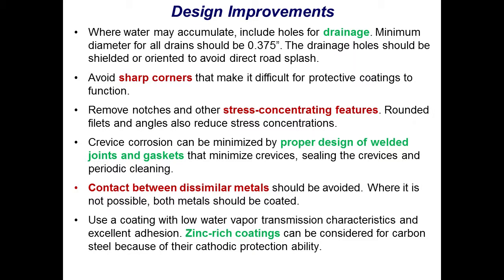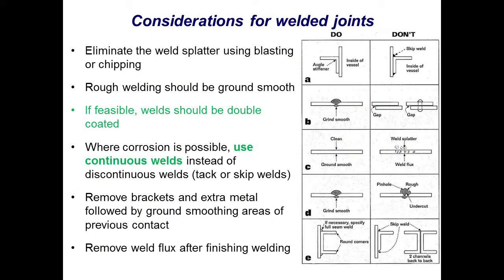Now, in the industry, it's very common practice to use zinc-rich coating. The reason is we have no confidence that without the zinc, the coating will do a good job. For instance, if that coating is dented, that area becomes a weak spot, and that case is probably not much better than without the coating. You have localized corrosion going on. It's a self-accelerating process. With the zinc, the zinc will sacrifice itself and pump some electrons to protect that hole, that dent. So it's very common practice nowadays. Now, in terms of the weld, there are many items we collected from literature and from the survey responses, but the bottom line is the welding process induces heat-affected zones. In those zones, you have a problem. By designing it differently, you can minimize the issue or the risk.